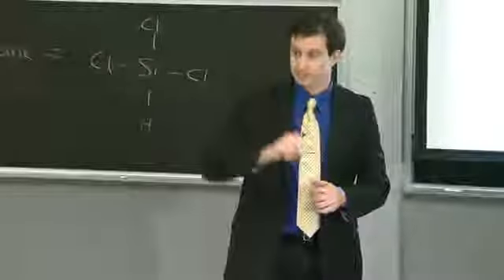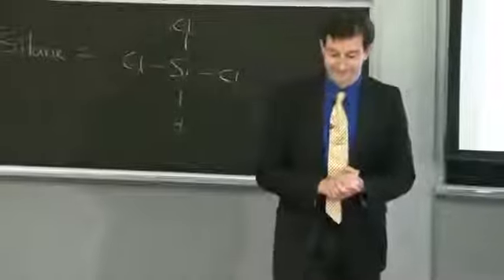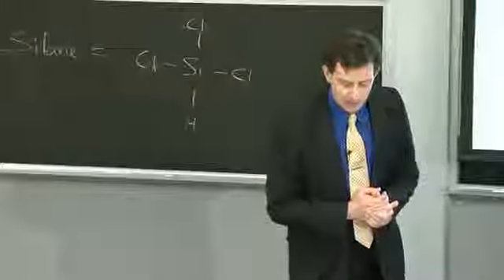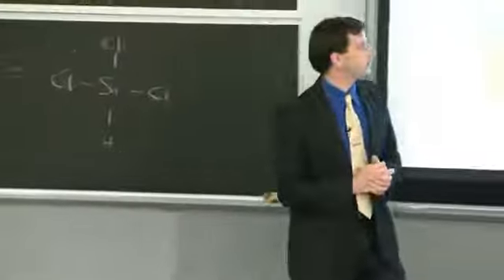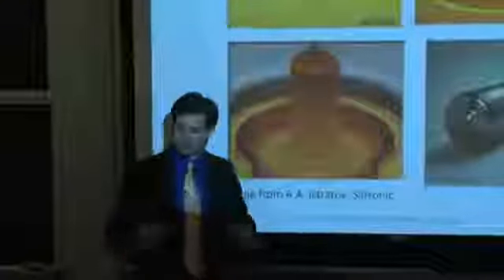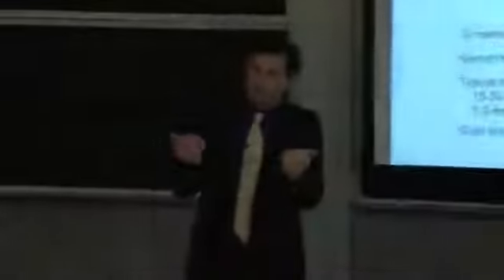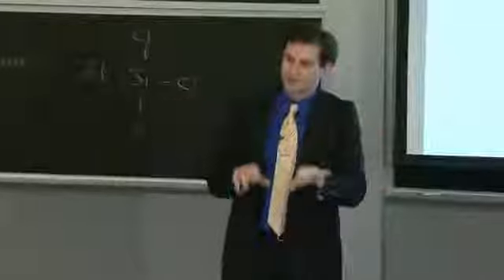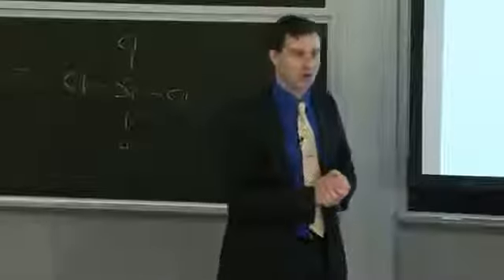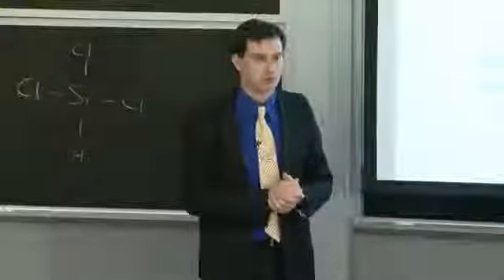Yeah, and then Ashley. Does the rotation speed just affect the diameter, or does it affect other things? So it affects a multitude of things. One of the things that it affects is the convective flow within the melt. So the liquid flow inside of the melt is in part determining how much oxygen gets transported from this crucible here into the growing crystal. If you manage to suppress that convective flow in the melt, you will also suppress oxygen transport, since the diffusion is going to be a lot slower than turbulent transport, or Marangoni transport, or convective transport.